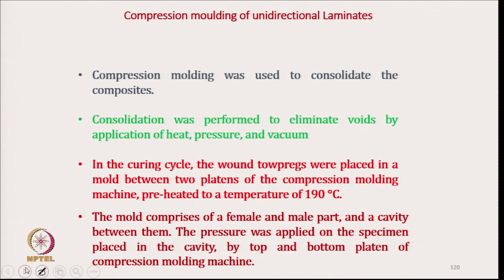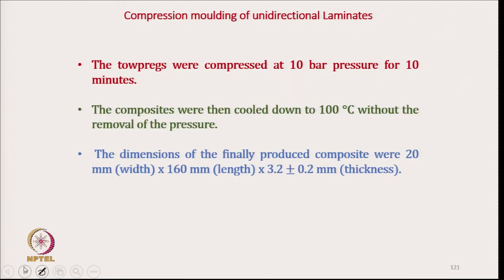The mold comprises a female and a male part, with a cavity between them. The tow was compressed at 10 bar pressure for 10 minutes. The composite was then cooled to 100 degree Celsius without removal of pressure. The final dimension of the composite was 20 millimeter in width, 160 millimeter in length, and approximately 3.2 millimeter thickness, plus or minus 0.2 millimeter.